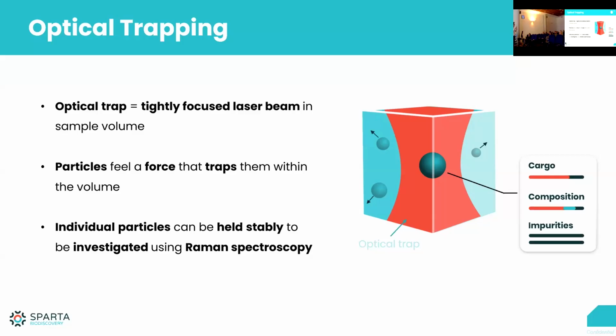And then the whole automation and the proprietary algorithms come in from SPARTA to make this all completely automated. So what was done before is you can trap one particle and have a Raman signal of that. Whilst that's interesting, it's not an analytical technique really yet, right? Because you have your formulation with your LNPs and you want to know what is the variation between all these particles. So we've made this whole complex process completely automated, which means that you can put your solution inside the machine, set a few parameters, press go, and it does all the interfacing and all the optical trapping, capturing data generation of single particles, all in a completely automated way. You can just walk away and then come back an hour later or so, and there's all your spectra from all your particles. So we make that part very easy.